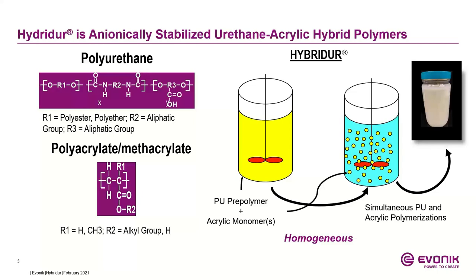Unfortunately, one of the main disadvantages of the aliphatic polyurethane dispersions is the relatively high cost. As a result, formulators have sought to reduce the cost by blending the polyurethane dispersions with an acrylic polymer emulsion that typically costs less than one half that of a standard aliphatic polyurethane dispersion. Although the acrylics reduce the system cost, the negative aspect is that it also reduces the overall performance of